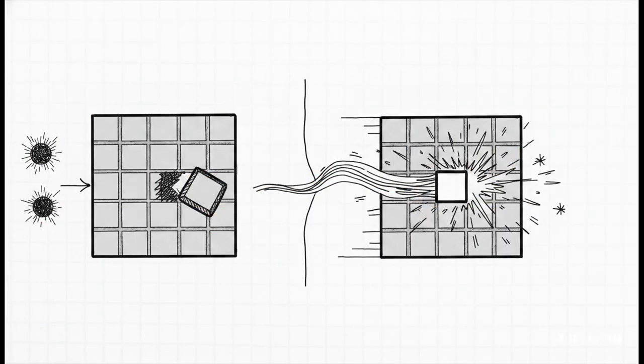But here's the catch. During the manufacturing of the raw powder, oxygen impurities from the air or even just moisture sneak in. And this is the crucial chemical reality. For every 3 oxygen atoms that manage to substitute their way into the nitrogen spots of the lattice, the crystal is forced to create 1 aluminum vacancy just to keep its electrical charge neutral. These missing aluminum atoms, these vacancies, act like massive potholes in our perfect crystal grid. When those high-speed heat phonons hit a vacancy, they scatter.